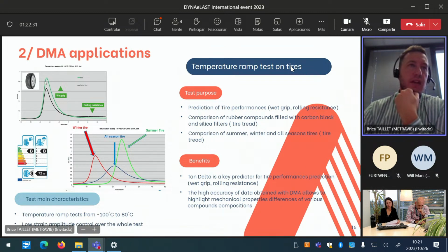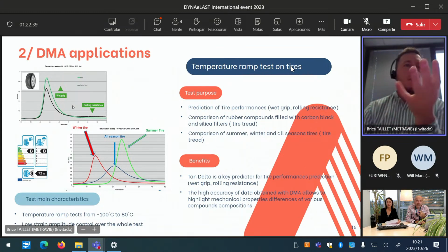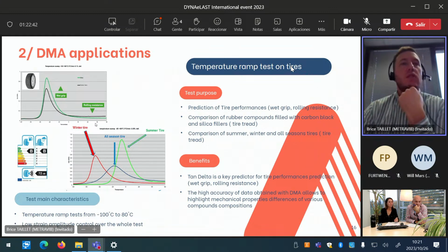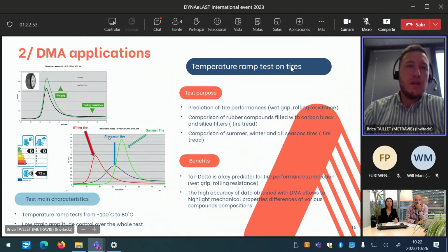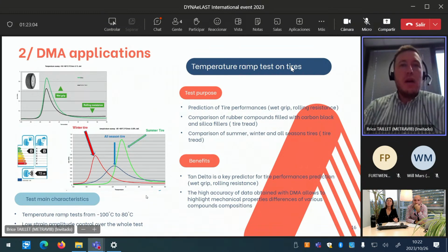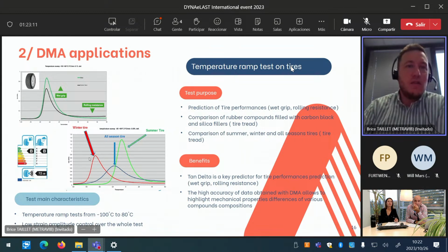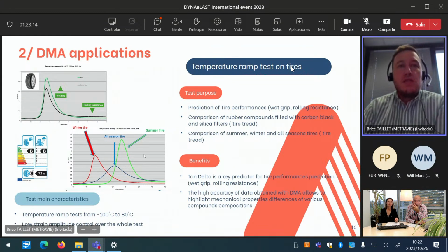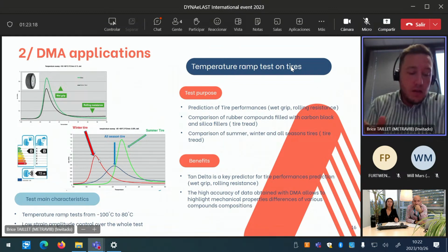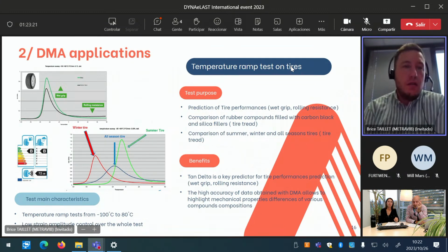And here in green, we have a tire with silica, for instance, and in black, you have a tire with carbon black inside, just to have the comparison regarding the grip in wet condition or the rolling resistance. One interesting curve as well is the characterization of different kinds of tire: winter tire, summer tire, and all-season tire. And you can see the tangent delta of this tire as a function of temperature. And you can easily imagine why it's really clever to use summer tire in summer and winter tire in winter, actually, because of the position of the tangent delta. And the position of tangent delta is, of course, depending on the performance of the grip of the tire as a function of temperature.